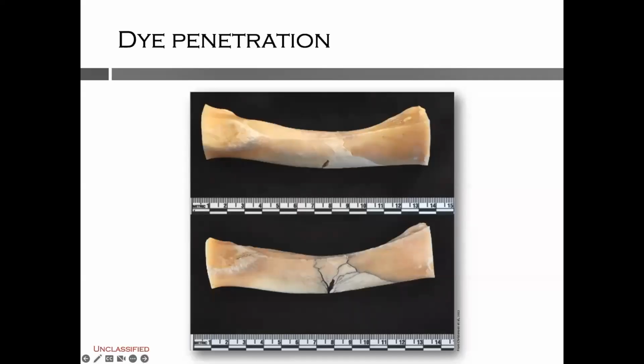The images on this slide show the same bone specimen before and after the application of ink. Ink was applied using a small paintbrush to the fractured area, and then a wet paper towel was used to quickly wipe away excess ink to avoid staining the surfaces. This was repeated along the fracture until all of the hairline cracks were highlighted. The result is a very clear picture of many small cracks that were not previously visible visually and certainly not in the photographs.